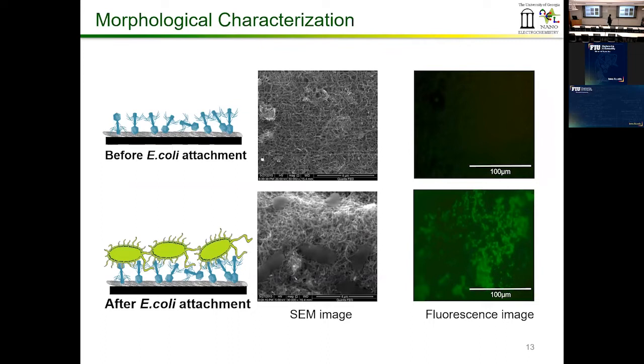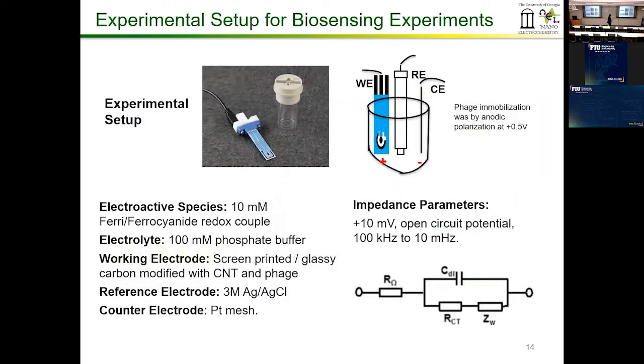So again, SEM just to show that yes, you have bacterial attachment. This is before and this is after, and you can see that yes, bacteria get attached to the surface. So we did electrochemical impedance experiments for all our biosensor characterization testing. These are just regular electrodes. They look very similar to your glucose test strips. They have 3 electrodes: working, counter and reference. The working electrode is the surface that was modified with the carbon nanotubes and then attached with the virus. The virus is actually present on the surface. And you do an electrochemical impedance test.